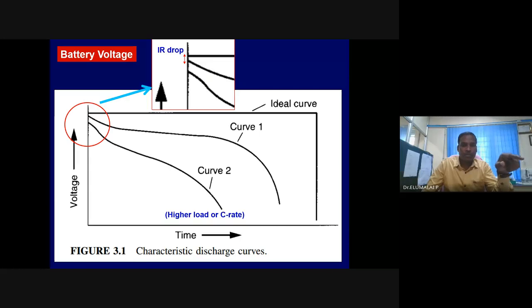4 hours of discharge. What is the capacity here now? Or maybe less than that, 5 times less than that. Instead of 8 hours, it may be 1 hour. Practically. So 1 ampere current delivering for 8 hours, capacity is 8 Ah. The same battery, if it is subjected to high load or high C rate, please wait, I will explain what C rate is later. 5 ampere current may be delivering for 1 hour. The capacity has reduced from 8 Ah to 5 Ah.